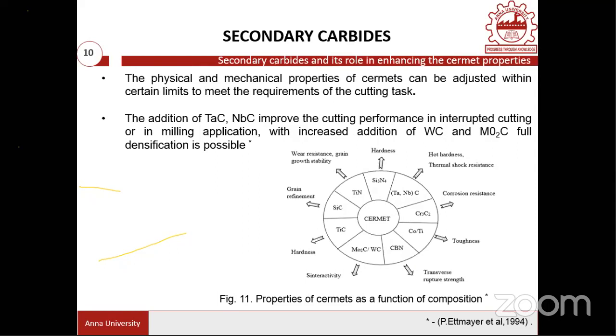So silicon carbide addition is a good grain refiner. Grain refiner doesn't mean that it is going to refine the starting material powder size. It will retain the starting material powder size. It won't allow grain growth to happen. So it is a good grain refiner. It will be sitting at the boundaries of two TiCN particles, and it will stop the diffusion. And then you have titanium nitride, which can also be added to improve the wear resistance, because nitride can improve the wear resistance and hardness. And also it is a grain growth stability material.